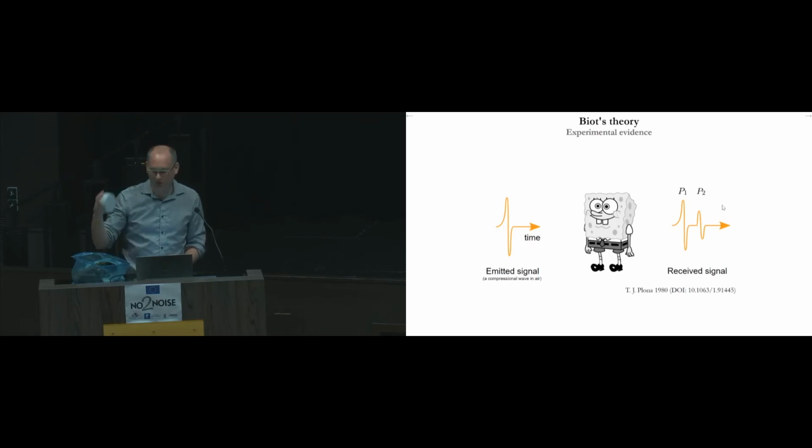while Biot was working on his work, oh, there may be a wave inside the frame of the porous material. So Leo Beranek, or people dealing with acoustic porous materials, were already seeing that, but people from the oil industry and geotechnics waited for the work by Plona in 1980 to just say, okay, we have 3 waves in a porous material: 2 compressional ones, and a last one which is usually called the S wave, which is the shear wave.